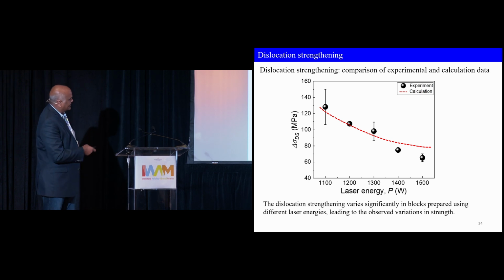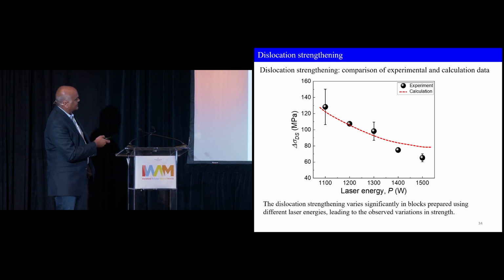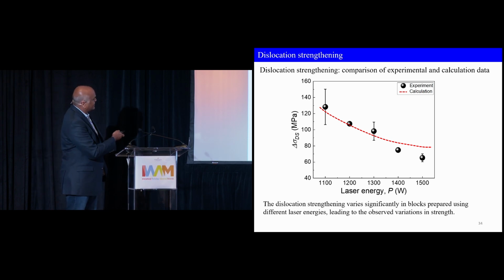This is from Taylor's calculation, and we show that we know the dislocation density - that is what I flashed in the previous slide - and we show that the additional strength actually comes from the large dislocation density.